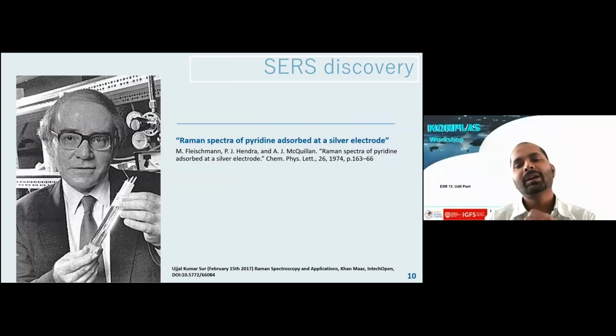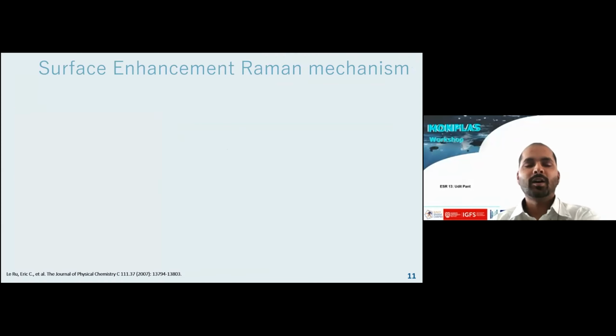Okay, so till now we have talked about how plasmonics helps in SPR based detection. Now, what happens when we combine this plasmonic effect with a Raman system? Then it is called surface enhanced Raman spectroscopy. Fleischmann and his group from the University of Southampton, UK, were the first group to report the enhancement in Raman signals in 1974. Although the enhancement was seen, how it was happening was wrongly interpreted until 1977. The precise mechanism responsible for the enhancement observed in SERS is still very controversial in the literature.